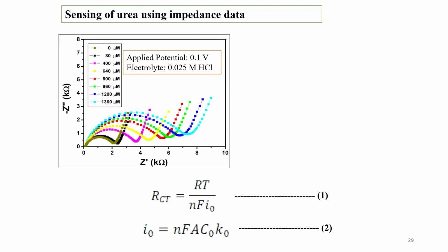Right. Now, here, whenever you are studying, let us say, urea oxidation, the reactant here is urea. Then, when you construct this type of Nyquist plot, you will have one intercept called RCT, which is the charge transfer resistance. And this number nearly 0 is called the solution resistance. So one is RS, solution resistance, one is RCT, charge transfer, and this is related to I0. This I0 is related to the rate constant of the urea reaction. So you are able to study the rate constant using the impedance technique. So here the reactant is urea. Similarly, in every case the reactant will be something else, ferricyanide or cadmium nitrate, something. So this I0 is referring to the exchange current density of the electron transfer reaction you are considering.